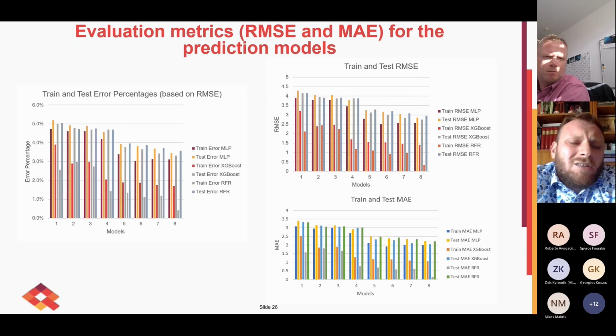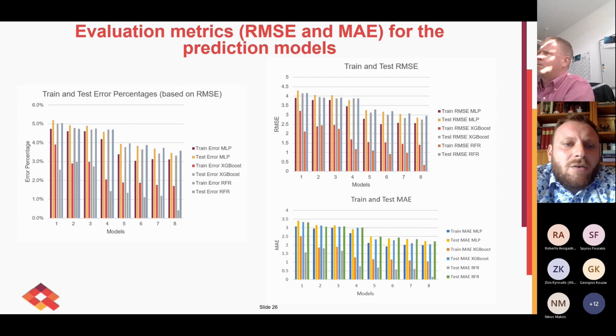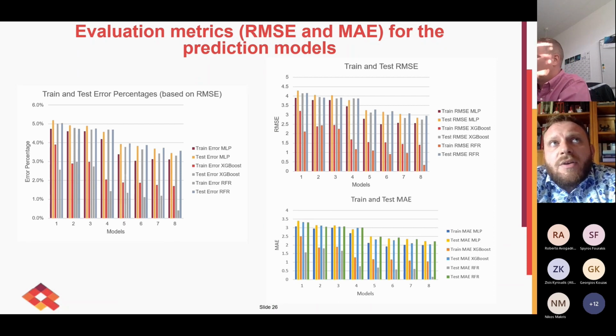We chose MLPs, as you can see, although they do not have the best test error. The thing is that they have a similar train and test error, and this indicates that overfitting has been avoided. Whilst in the other methods that were tested, XGBoost and random forest regression, you can see that the train error has a high difference from the test error, and this signifies that there is overfitting.